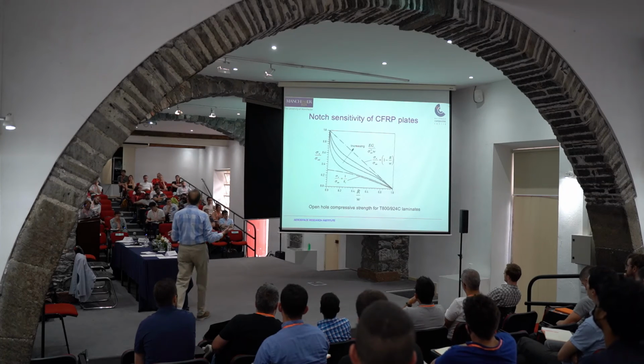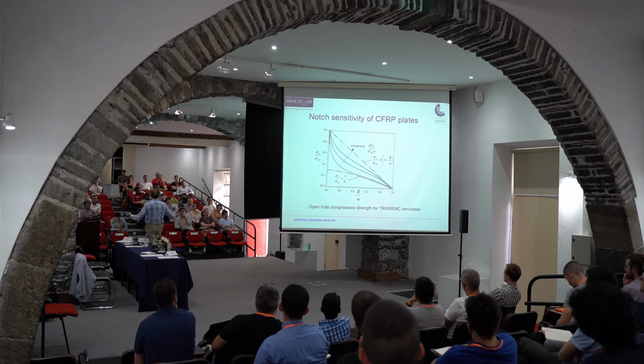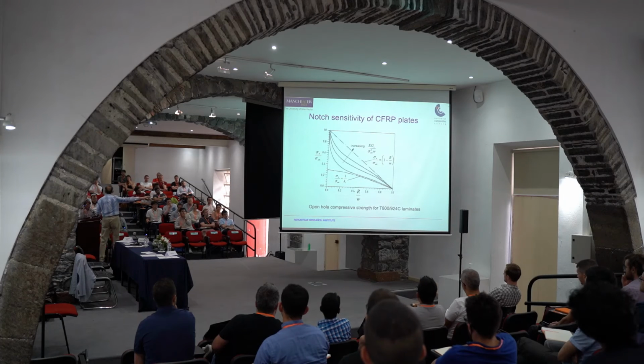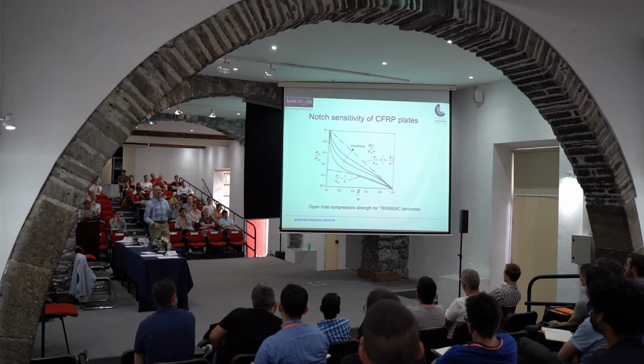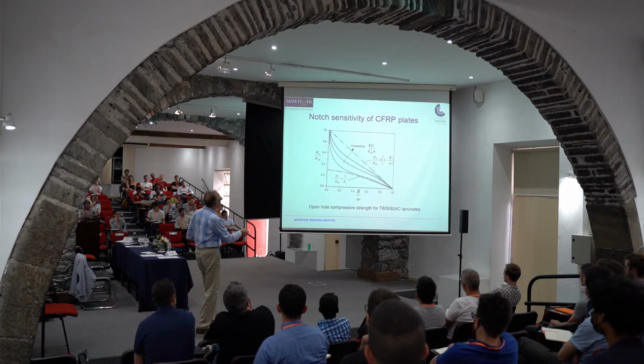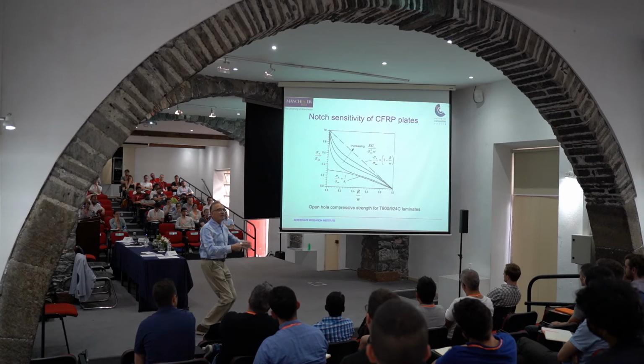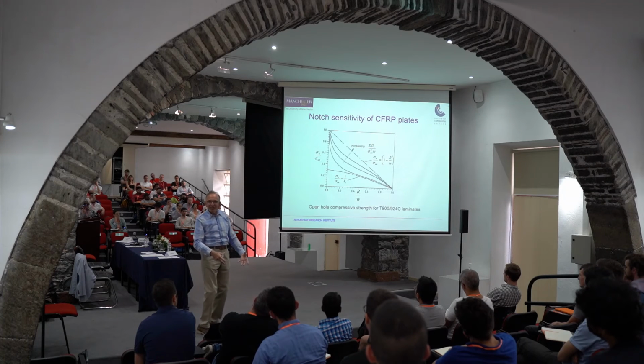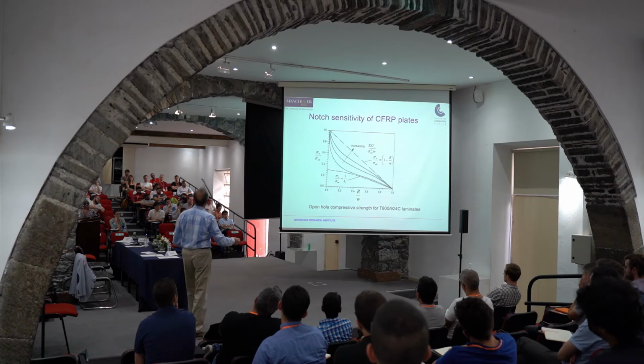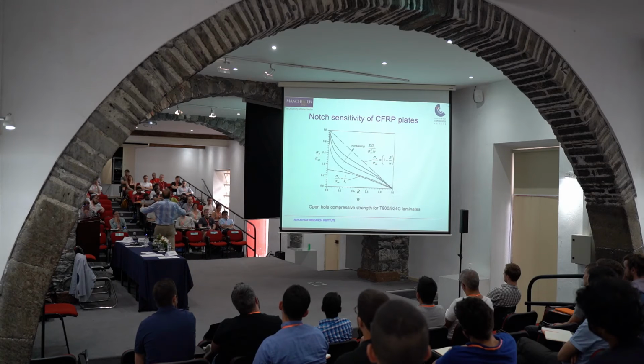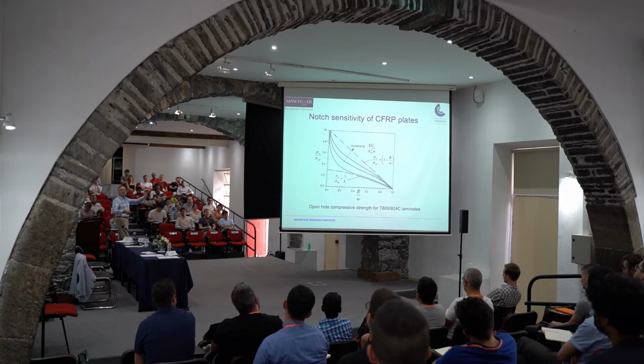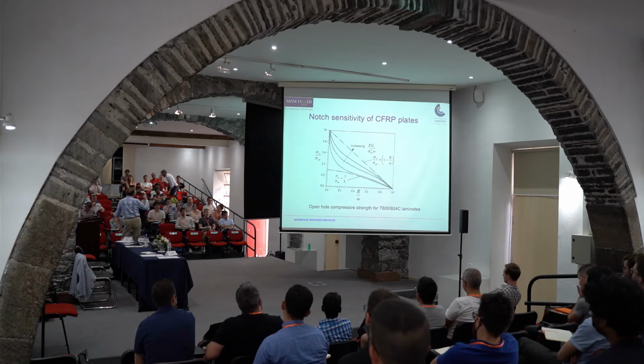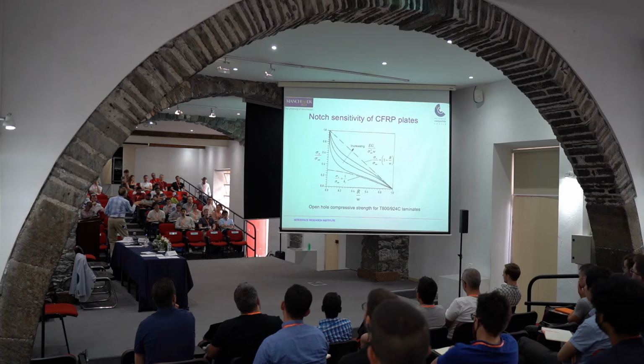And here, that's the most important one. If you look at metallic plates with an open hole, you have two criteria. One is the ideally notch sensitive, which is the bottom one. Sigma notched over sigma unnotched varies with the stress concentration factor, 1 over kT. So this is the notch sensitive. The bigger the hole, the bigger the stress concentration, the lower the strength. And this top one is the ideally notch insensitive, which means that sigma notched over sigma unnotched varies with 1 minus R over W. R is the hole radius, and W is the half width of the plate. Yeah? So you remove more material, linearly your strength is reduced by that amount.